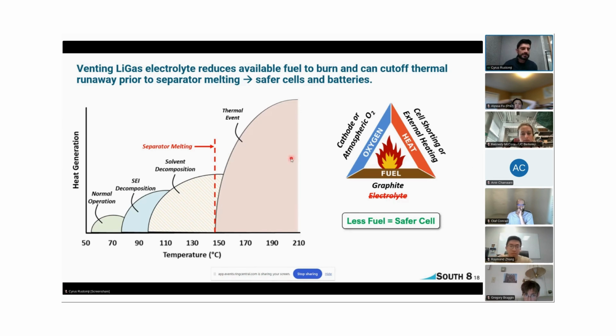Essentially, here's a map of heat generation on the y-axis, qualitatively speaking, mapped against temperature. You have your normal operation up to about 60, 70 degrees, which thereafter you begin seeing SEI decomposition. Once you get hot enough, you start to get solvent decomposition on those anodes and cathodes, which really drives your thermal runaway reaction until your separator melting point, right around 150 degrees Celsius, which then short circuits your cell and drives thermal runaway.